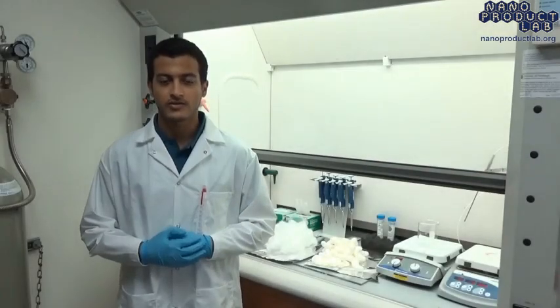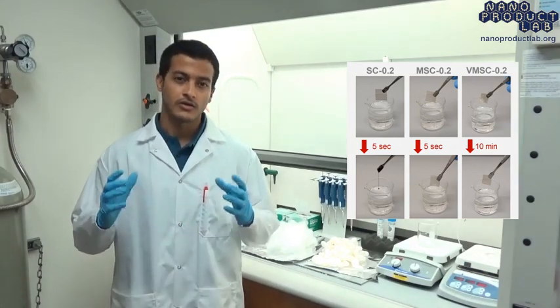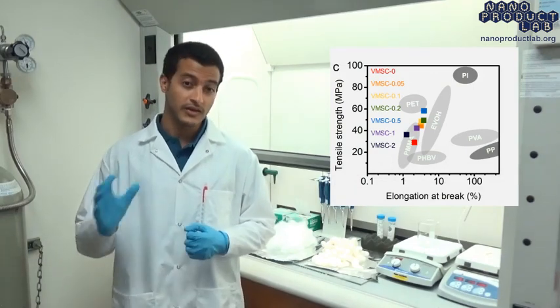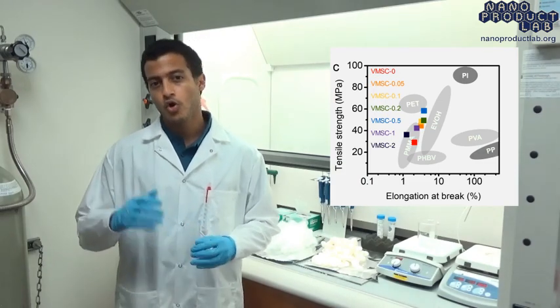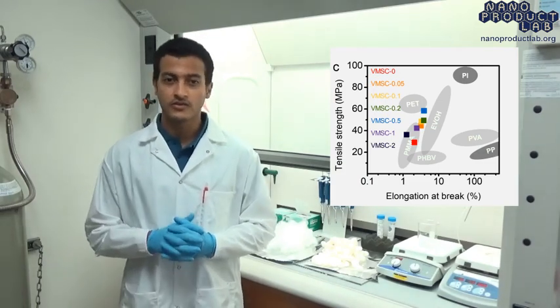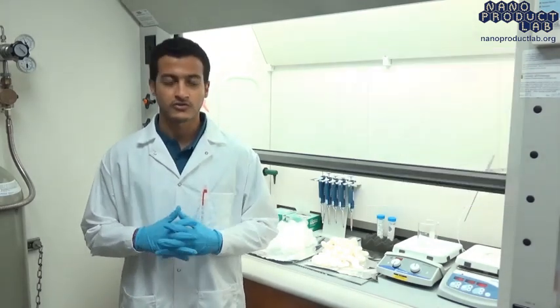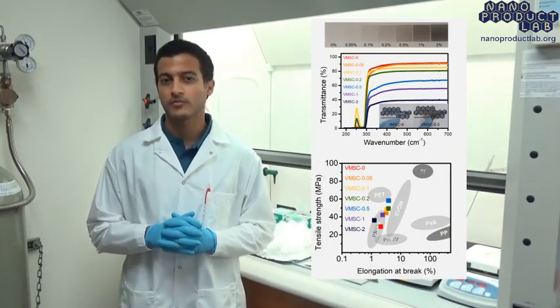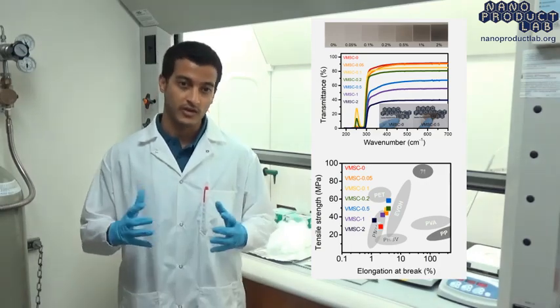Our films exhibited enhanced water degradation resistance and tunable mechanical properties. The films also exhibited enhanced mechanical properties like 90% increase in mechanical strength and an 80% increase in elongation owing to the synergistic CNT reinforcement effects and the ductile properties of the alpha-helix structure. The mechanical and optical properties of our films are comparable to synthetic polymers such as PET with the added advantage of better sustainability and biodegradability as well.